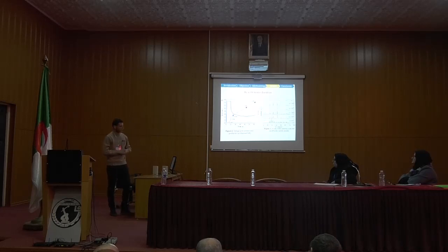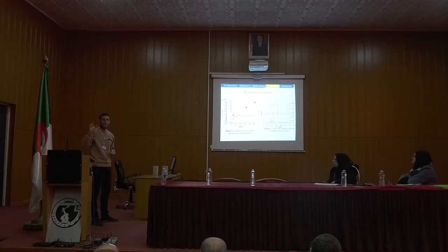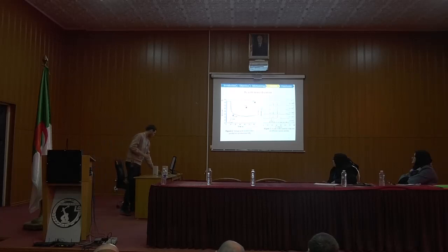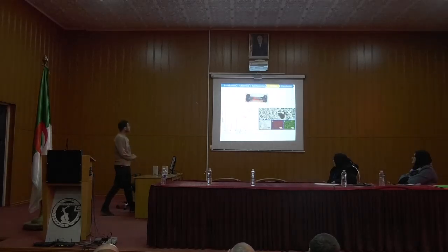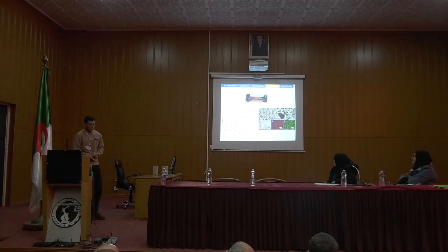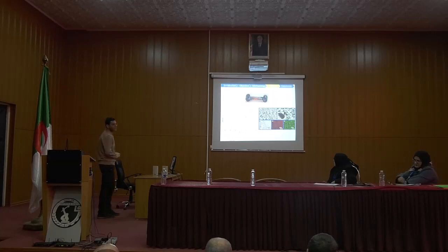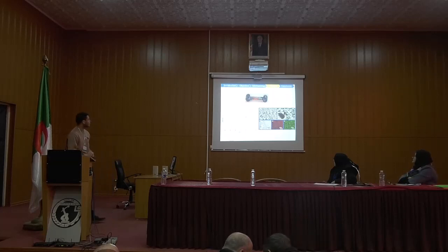Also, something important to notice is that the reaction happened in only 1 minute. 1 minute was enough to produce the material. So this is the sample. For the next analysis, we perform an X-ray and also an AFM analysis of the sample.